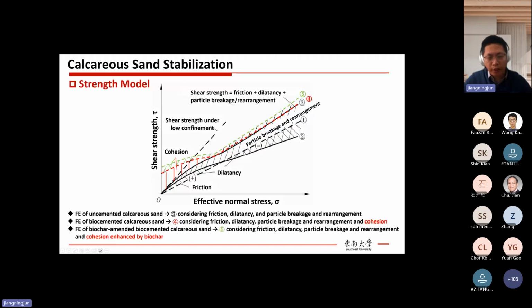Then if we further consider the contribution of biochar, so this is the green line. Firstly, at low effective normal stress range, biochar could lead to more cementation. So we see more increase in cohesion, as you can see here.